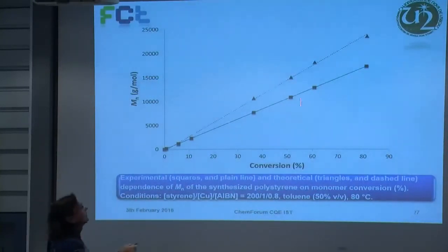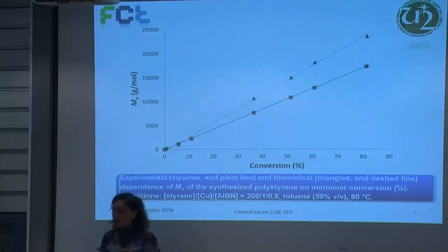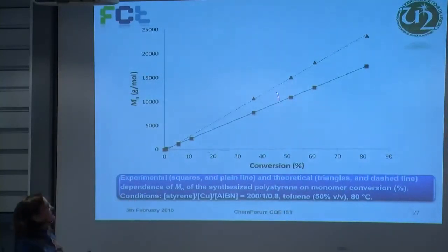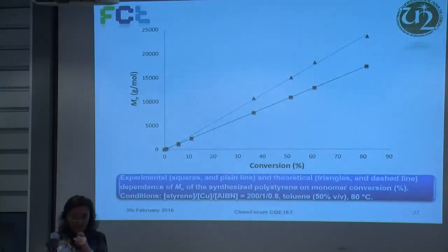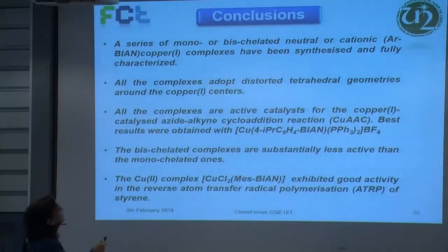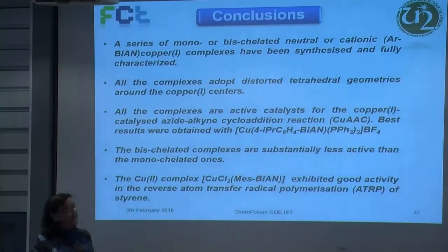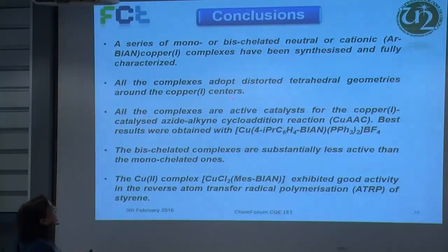And we can see from these results that the polymerization is controlled. So we conclude that we have synthesized a series of mono or bischelated neutral or cationic BIAN copper(I) complexes, and we fully characterized them. All the complexes adopt distorted tetrahedral geometries around the copper(I) centers.